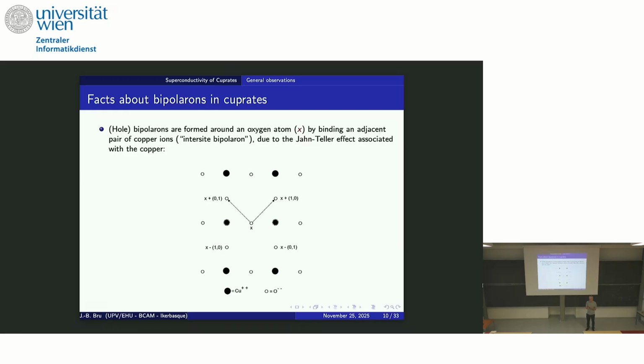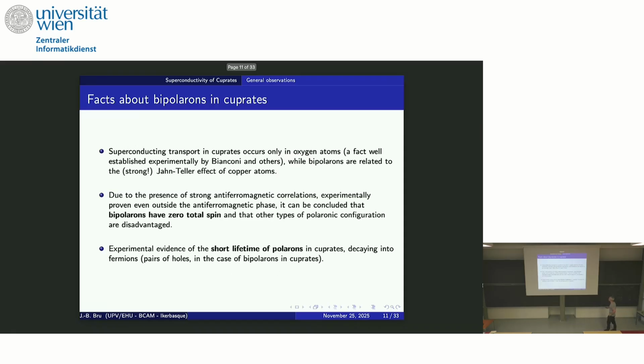They also estimate that the bipolarons are not stable. They do not stay forever; they are relatively unstable. So your two electrons get trapped, and then you get a bipolaron, which you could model as a caricature as bosons. And sometimes they are released, and then you again have conducting pairs, which are moving. So that's the picture. What I am saying here is that it occurs only in oxygen atoms, bipolarons have zero total spin, and there is experimental evidence of the short lifetime of the polaron in cuprates, decaying into two fermions. So that's three facts that I already mentioned.